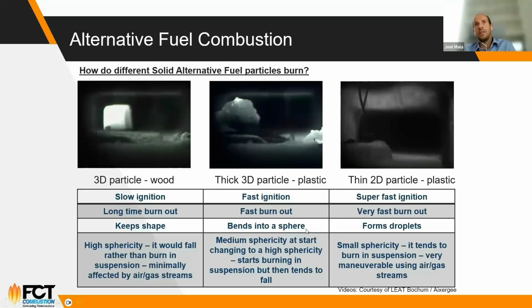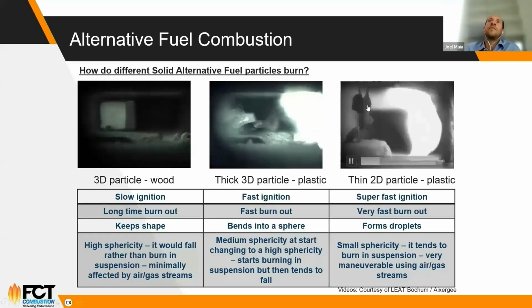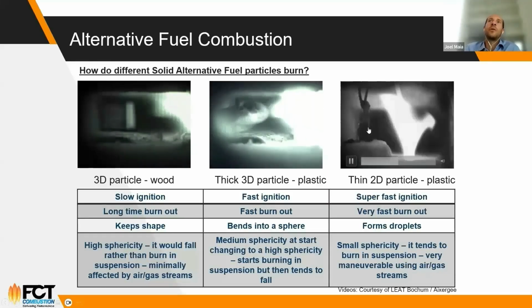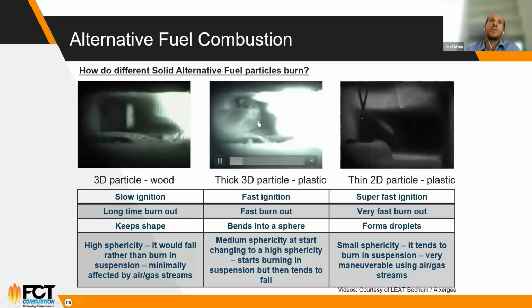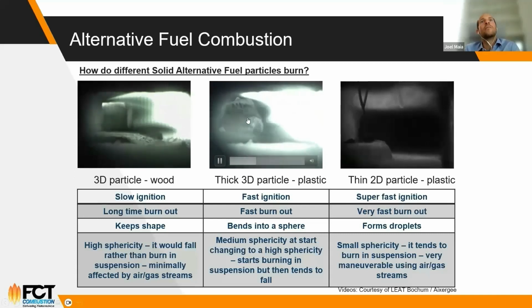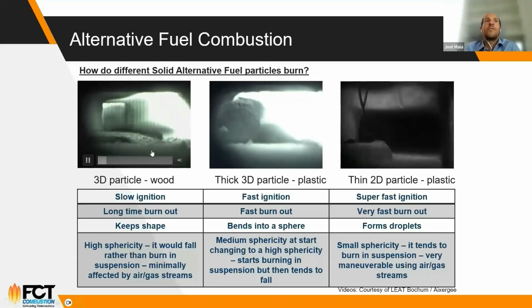Here we would have a very low sphericity, and here we would have a very high sphericity. So if I play this again very quickly, you can see that here it started very fast and it has already formed some droplets and it's finished. Here this particle is curling around itself, forming a sphere more or less, and then it's also finished soon. And here this is a very stable material, it doesn't change its form, so it will stay there for a long time, as you can see here. We don't have time to see the whole video, but you get the point.